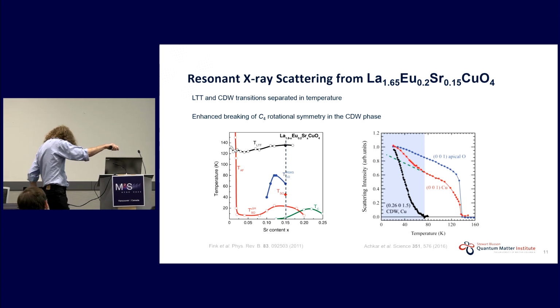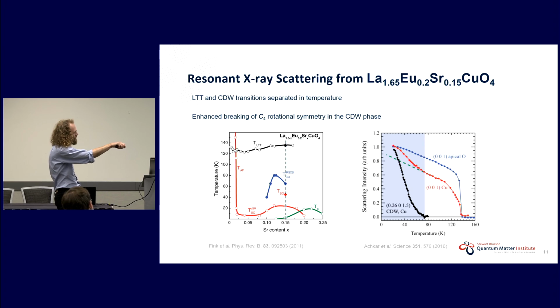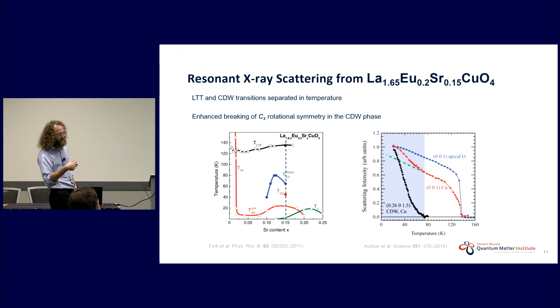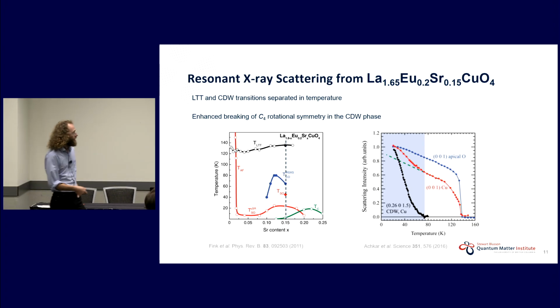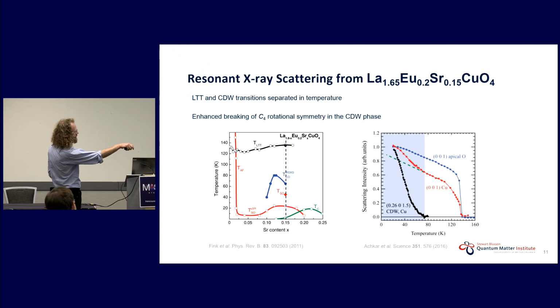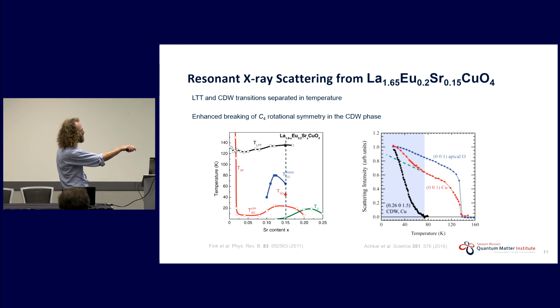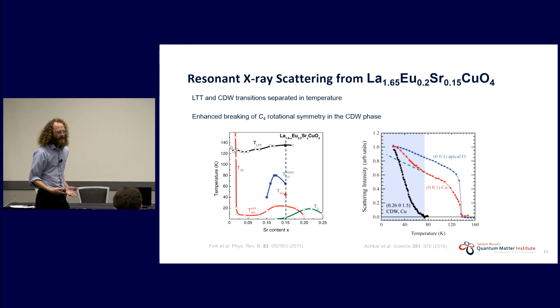If we go to the copper L3 edge, then we see the same thing, so rotational symmetry breaking associated with the LTT distortion, and then a lower temperature associated with the onset or correlated with the onset of translational symmetry breaking in the CDW phase. We get additional intensity coming up in this 001 peak associated with the rotational symmetry breaking. So that says we have now a resonant X-ray scattering signature, this red one at the copper edge, which has two components, an electronic component associated with the rotational symmetry breaking driven by the CDW, or the nematicity driven by the CDW, and a component down here which is associated with the structural anisotropy, okay?